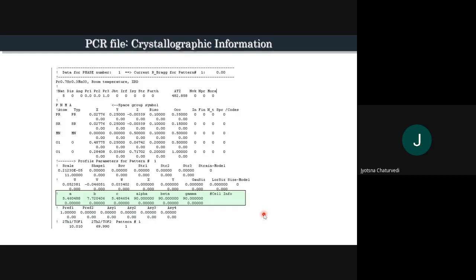So we don't know where the material will move, but in the XRD pattern, the dominating phase we are getting, like we are saying that the 100% intensity peak matches with the hexagonal phase, but still it is shifted, because alloys do not give a perfectly complete peak shift all the time. They are slightly shifted also sometimes. So in that case, how will we generate the CIF file and how will we proceed with that?